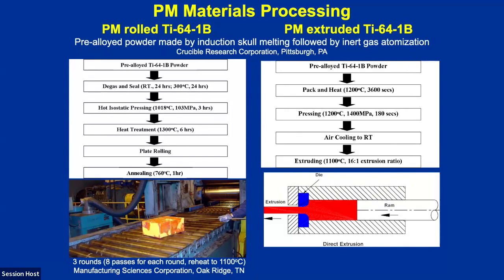We've seen a lot of talks about processing, and this is no significant difference in that. This is the rolled. We typically have a rolled billet, we go through rollings, and we can reduce it without seeing much cracking at all. And same thing with extrusions. We're going to talk about differences in the texture that were caused by the rolling versus the extrusion, where the extrusion resulted in a significant change in the texture compared to the rolled material.